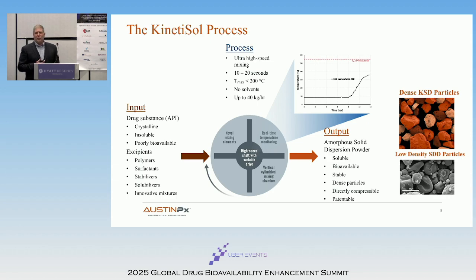Your output is an amorphous solid dispersion that behaves a lot differently than spray-dried particles. Spray-dried material tends to be fluffy, low density, and difficult to handle. The KinetiSol particles are dense. They could be directly compressed into a tablet. You don't need to do additional handling. And then you get the solubility increase as a bonus because the material is amorphous.